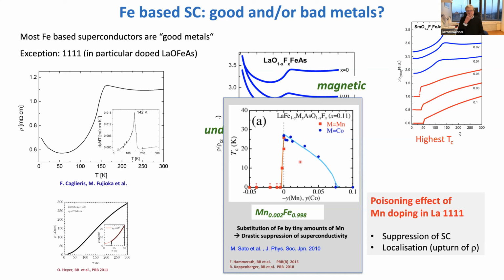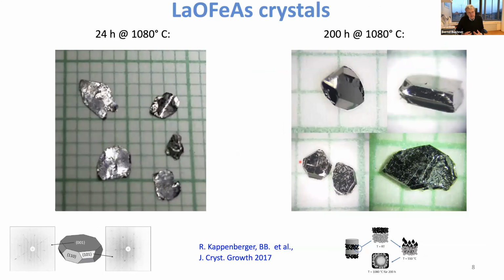Okay, so that's background. So the big step which we made in crystal growth was done a couple of years ago. It's a very unusual procedure, a so-called solid state crystal growth procedure, which allows us to grow pretty nice, well-faceted single crystals, three-dimensional single crystals. That was first done on 1111 type crystals, so on the parent compound of these compounds, and it's still an ongoing procedure. It's a very complicated process, and we are still not completely happy, and we are still improving this thing. But this shows the potential that you can really do single crystal studies, which gives much more insight into the properties of these systems.